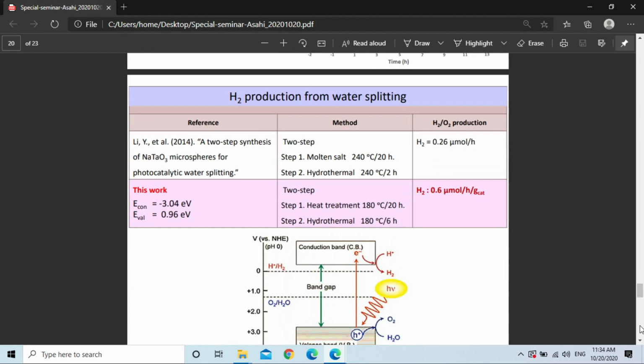Finally, we measured the hydrogen production of this sample, and we found that we can get hydrogen production, but the amount is still very small. Anyhow, when we compare with the previous research, the reference paper that we follow, we use a lower temperature, but we can get higher activity of hydrogen production. We also calculated the band structure, and the conduction and valence bands of this material cover the potential for hydrogen production from water.